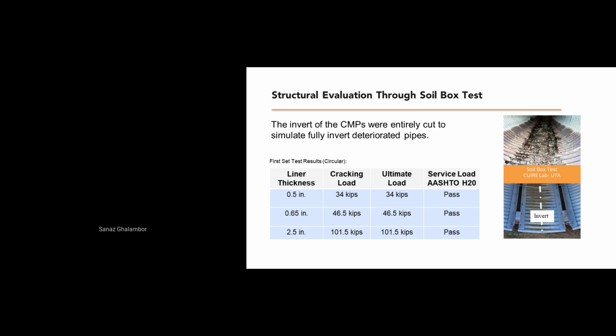So we continued loading until the failure happened. The failure, or the ultimate load or cracking load, was reported. The failure was because of cracking on the crown of the pipe, only longitudinal cracking, no circumferential cracking. And the results were very impressive. In this picture, you see what I mean by not having an invert. So the invert was cut so that we can simulate the fully invert-deteriorated pipe.